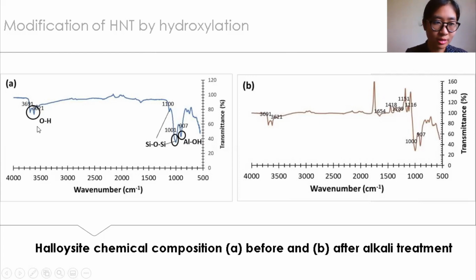Observed at higher wave numbers, around 3600, are also 2 strong peaks, which correspond to the stretching vibrations of the oxygen-hydrogen bond in the inner surface of the halloysite's tubular structures.